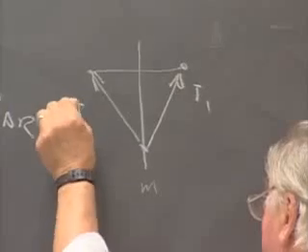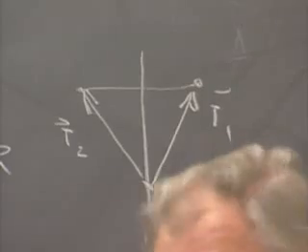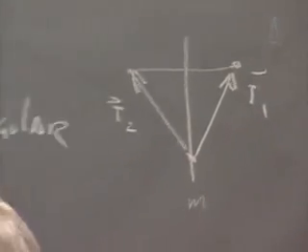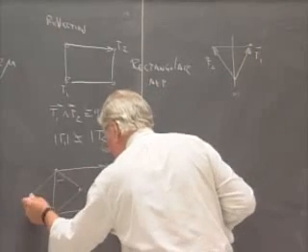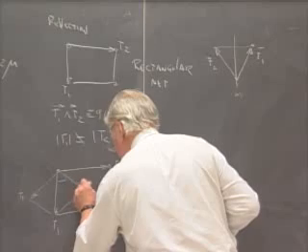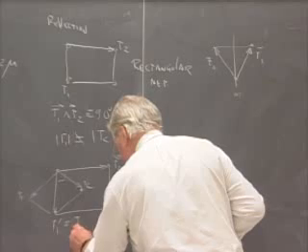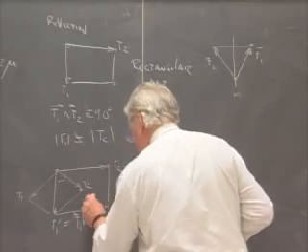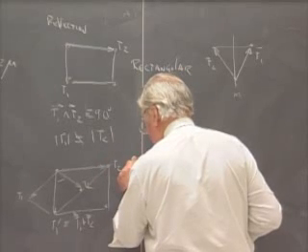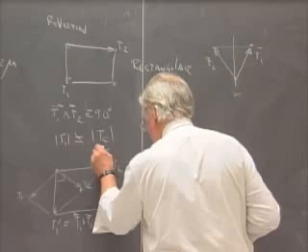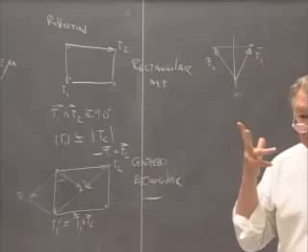So here's a first translation. I've got a second non-collinear translation. Whammo, instant lattice. So what I'm doing is taking this diamond shape, and I'm taking one translation here. Let's put some labels on this. Let's call this T1 and this T2. So this translation here, call it T1 prime, is my original translation T1 plus T2, and this translation T2 prime is going to be minus T1 plus T2. So I've taken linear combinations of the two vectors of the diamond-shaped cell.